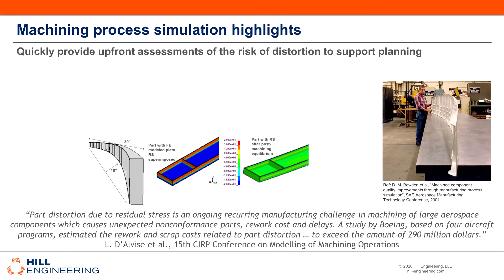One of the first ways that we can help is by providing upfront assessments of the risk of distortion for potential new products. This identifies parts that will be difficult to machine — it's a major help for, say, a contract machining vendor. The example shows an aerospace machined part that distorted after being unclamped from the table. You can see there's quite a bit of curve in the machined part, which wasn't the desired result. The simulation determined about 18 inches of out-of-plane displacement near the mid-length of this 30-foot-long part.